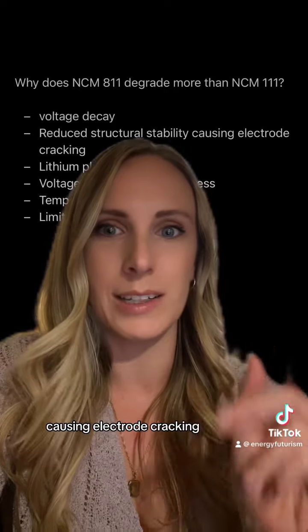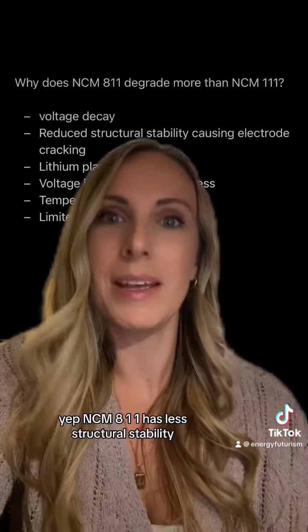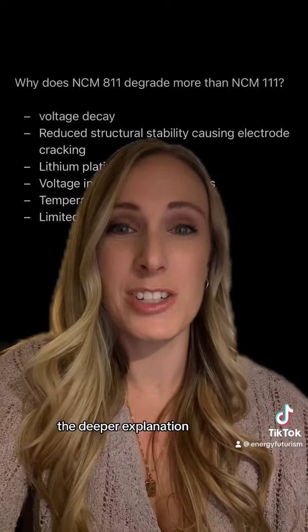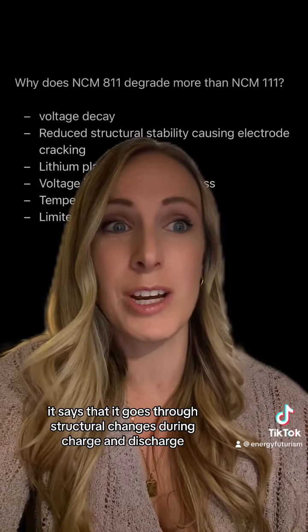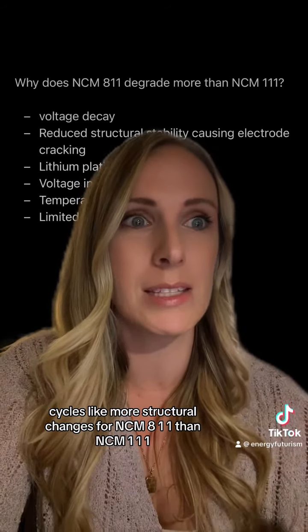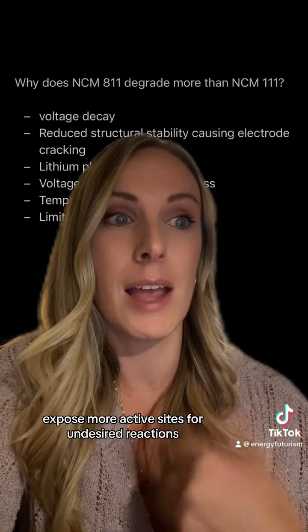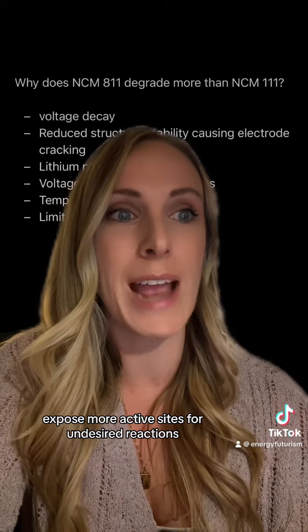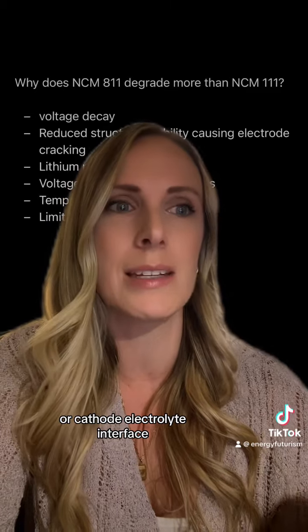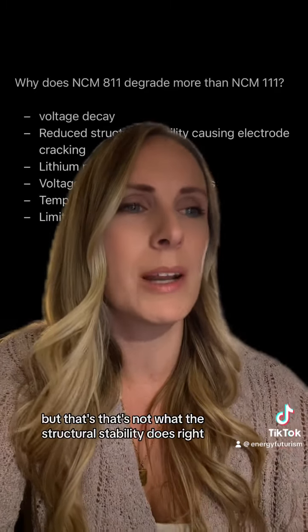Okay, the second one, reduced structural stability causing electrode cracking. Yep, NCM811 has less structural stability. The deeper explanation is that it goes through structural changes during charge and discharge cycles, more structural changes for NCM811 than NCM111, which is kind of true. And it says those structural changes expose more active sites for undesired reactions, which I think means CEI formation, or cathode electrolyte interphase reactions. But that's not what the structural stability does, right?